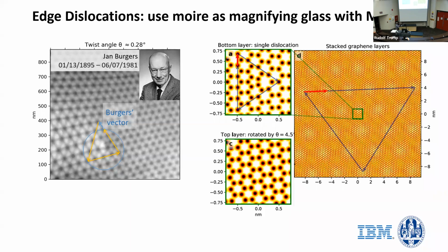this is the bottom layer of graphene. You see a 5-fold and a 7-fold ring here. So this is the core of the dislocation. You can again do a Burgers circuit, and you find that this is the Burgers vector of this dislocation. We put the top layer of graphene on, rotated just for illustration purposes here by 4.5 degrees. And here in the Moiré lattice, again, you see a dislocation and you can determine the Burgers vector. Interestingly, in real space, the atomic Burgers vector and the Moiré Burgers vector are rotated by 90 degrees. So this Burgers vector here tells you that the atomic scale dislocation is normal to it.